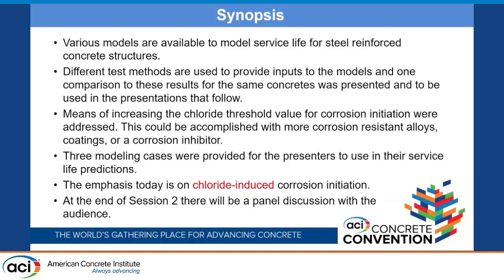So basically, what happens is two things. You run out of hydration of the cement, and two, your water cementitious ratios are so small that you can't even get the water into the cement. So a lot of these things are also more applicable to higher water contents that would have been used. And if you look at it, some of these models are good between 0.40 and 0.60, where they had data, but it was data that was kind of old. So the model itself was a good model, but how long some of these things go on might be dependent on the fact that we have different materials today than we had when the long-term data went into the model. Okay, I hope that answers your question.